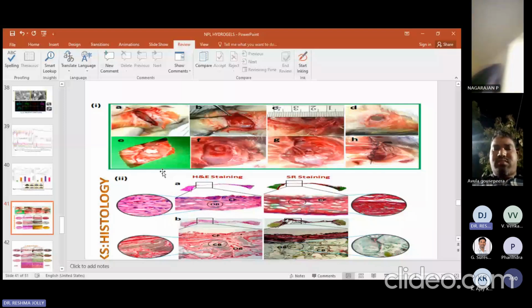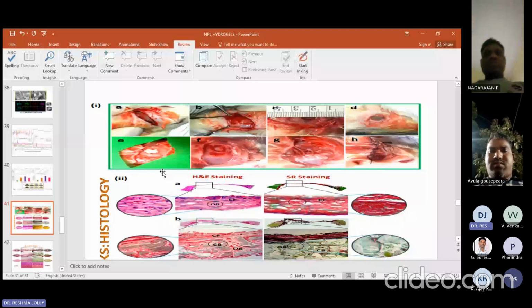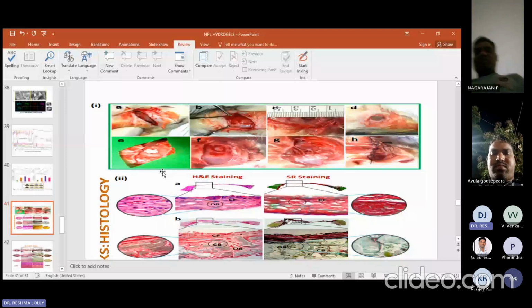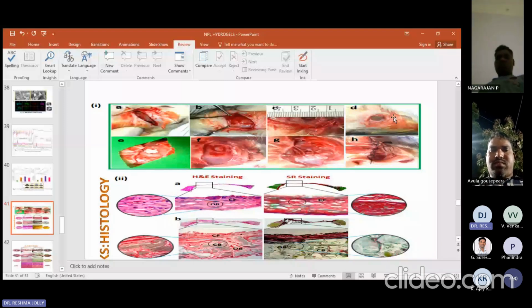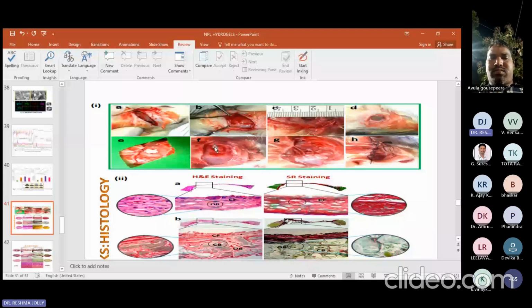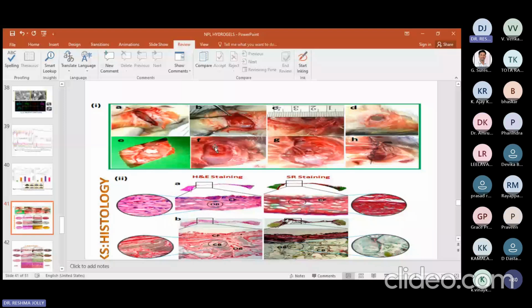So for that, ruling out that problem, I took Cerabone. Cerabone is a very famous dental bone filler. This is the defect filled with Cerabone, this is the defect filled with our material, and this is the defect left empty, to notice whether the defect heals up naturally and in how much time. Then we made a resorbable stitch, and these are the results.